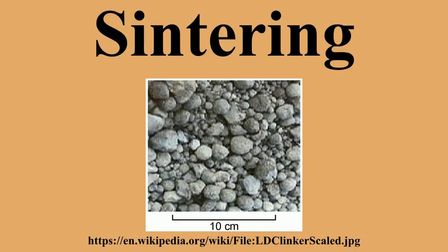All the characteristic temperatures associated with phase transformation, glass transitions, and melting points, occurring during a sinterization cycle of a particular ceramic's formulation can be easily obtained by observing the expansion temperature curves during optical dilatometer thermal analysis. In fact, sinterization is associated with a remarkable shrinkage of the material because glass phases flow once the transition temperature is reached, and start consolidating the powdery structure and considerably reducing the porosity of the material.